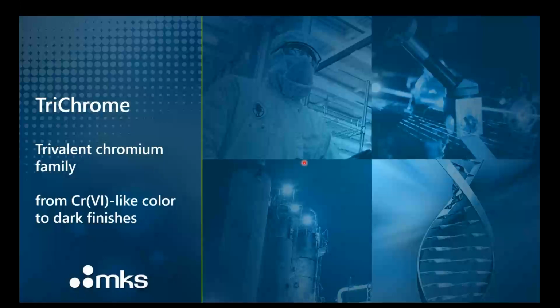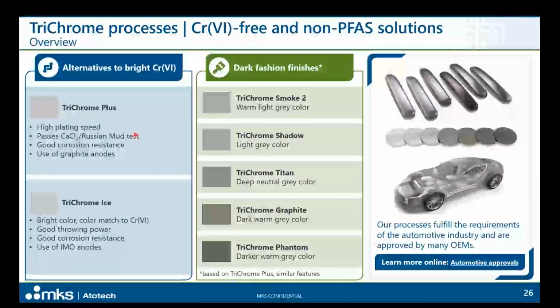And here we want to introduce the Trichrome family, the different processes that MKS Atotech can offer to you, from the chrome 6-like color to the dark finishes. In this case, we can propose two alternatives. One is the direct replacement for the bright hexavalent chromium, and for that, we can present the Trichrome Plus: high plating speed, excellent results in the calcium chloride test, good corrosion resistance, working with graphite anodes. And we can also propose the Trichrome Ice, especially when we intend to target the brightest color possible and a color to match the benchmark color from the chrome 6. The throwing power is very good, with excellent corrosion resistance, and in this case, working with mixed oxide anodes.